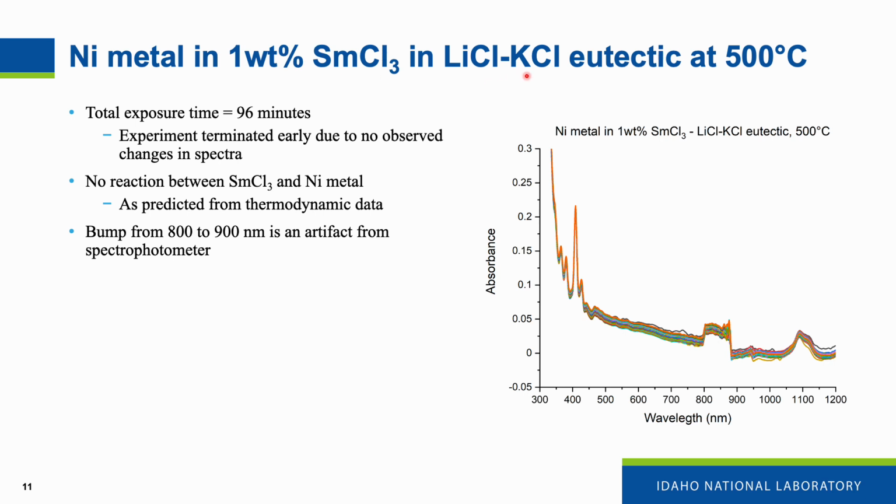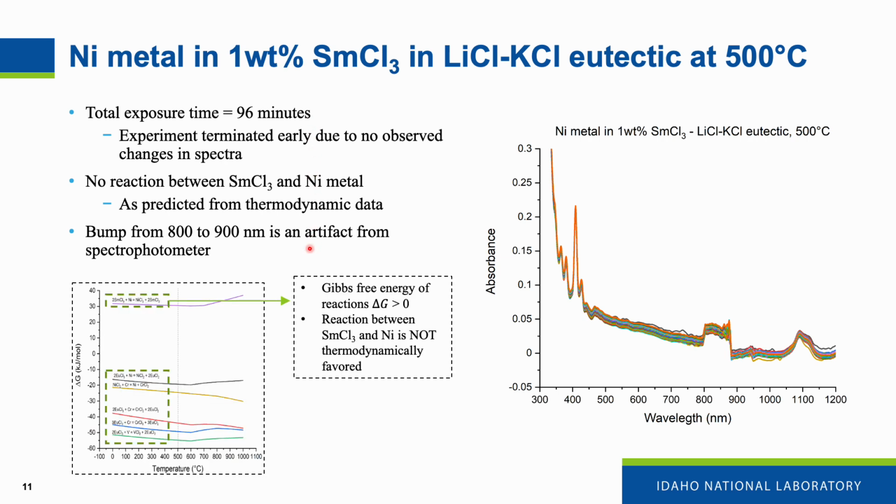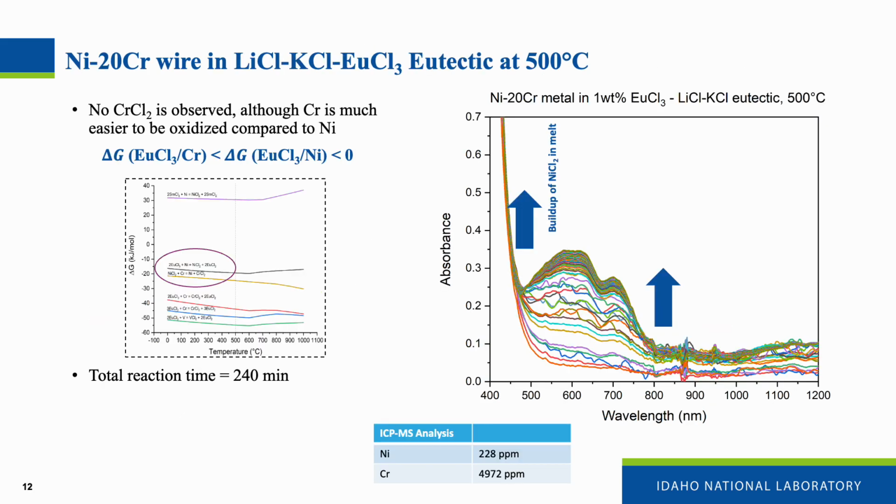So we went back to the LiCl-KCl eutectic system, and in this case we loaded 1 weight percent of samarium chloride instead, and then we dropped in a nickel wire. In this case we did not see any buildup of nickel. After about 96 minutes, we terminated the experiment since we were not observing any change in the spectra. But again, we don't expect thermodynamically any reaction between samarium chloride and nickel metal. So this is what we were expecting.